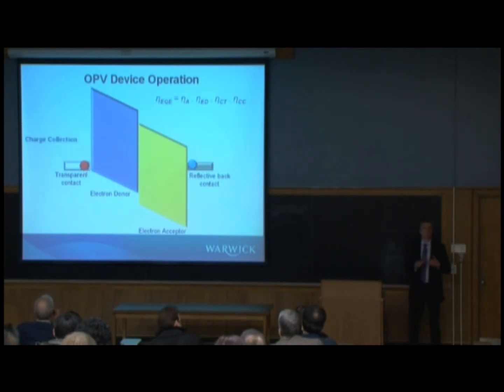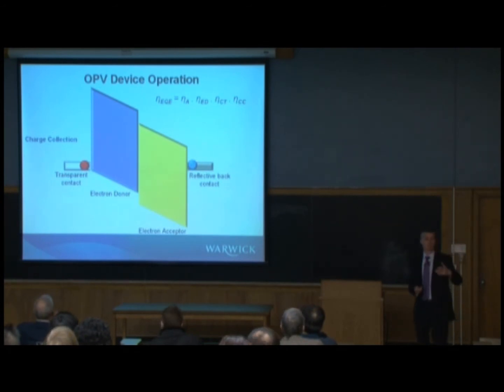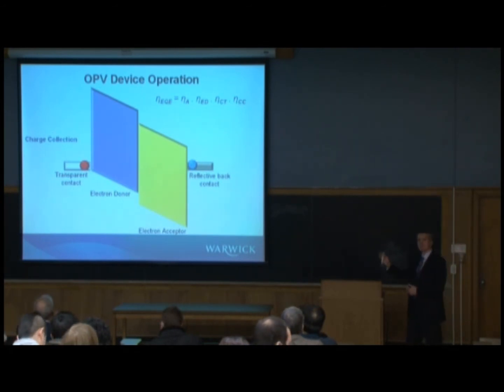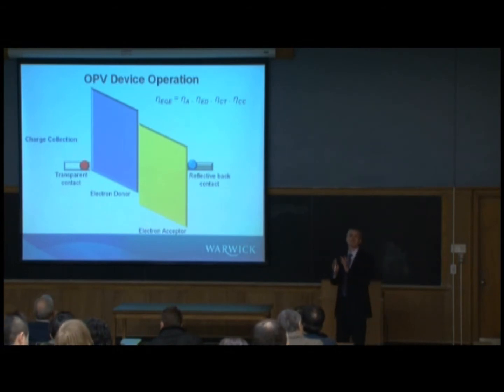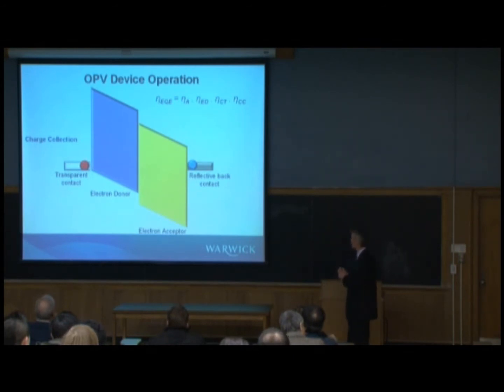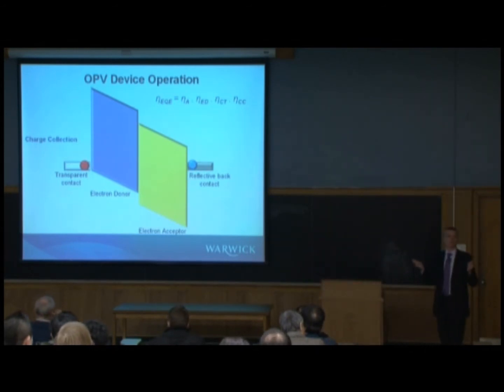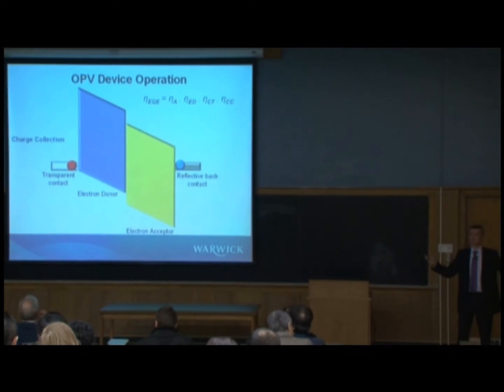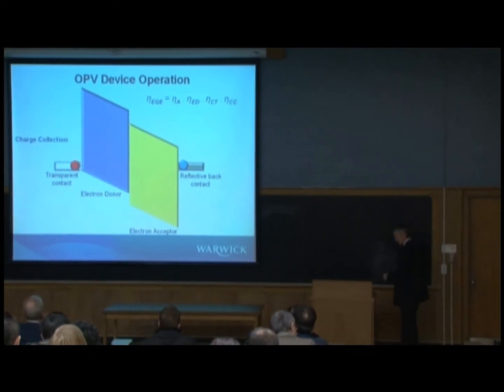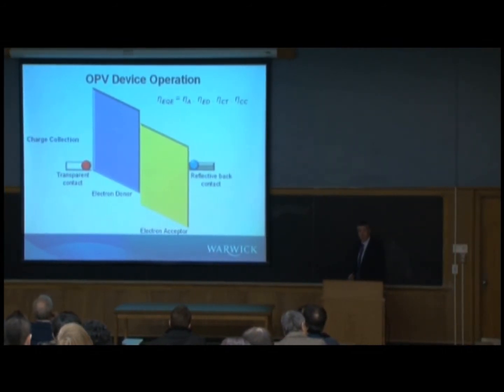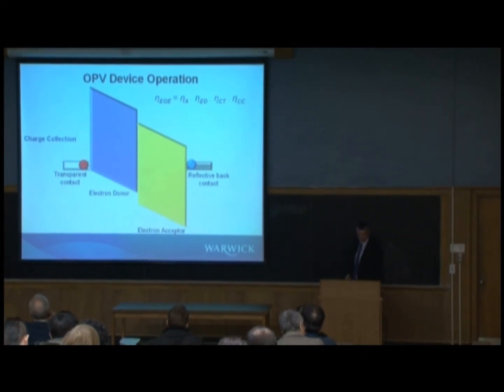So that's the basic operation of an excitonic solar cell. Generation of the exciton, so absorption of the light, diffusion of the exciton to the interface, so you have to have these interfaces between different materials, and those interfaces have got to have the right energetics in order to dissociate the exciton, and then transfer charge carriers through to the electrodes to generate the current. So a very different operation to a conventional PN junction silicon solar cell.